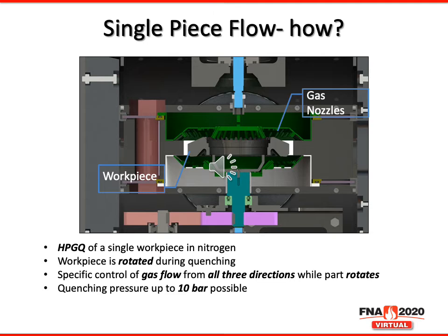In this process, the part cools rapidly, and meanwhile it rotates, further allowing the part to cool in a more uniform fashion. So, to summarize, the part is being impinged by gas from all sides and is moving through that gas flow field, and cooling at the same time. The key process variables are the gas pressure, the gas velocity, the nozzle pattern, the rotation, and time. Now, of course, all these items can be varied and are depending on the part material and geometry.